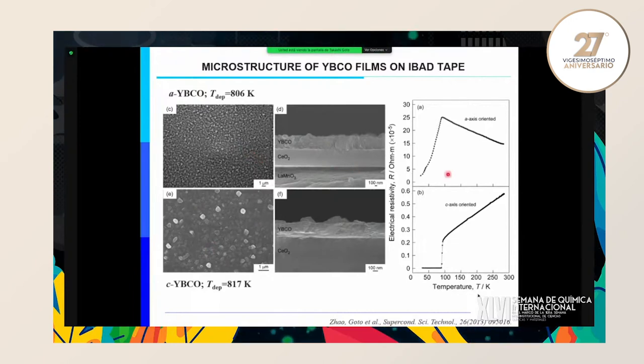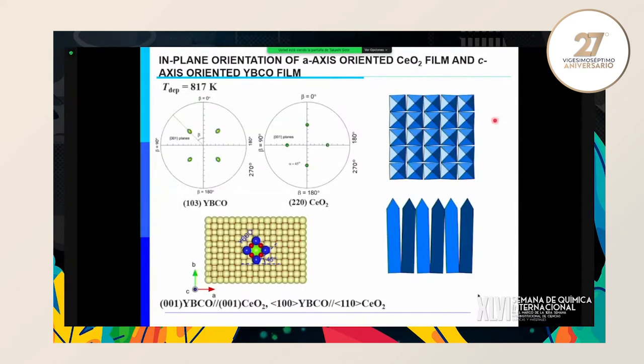But the superconducting critical temperature of A-axis oriented YBCO is low, while C-axis oriented YBCO is high enough, about 90 K. So we have to make C-axis oriented YBCO film. The ceria and YBCO film have the same single crystalline orientation: the YBCO 001 plane is parallel to the ceria 001 plane. It looks almost single crystalline by pole figure, but is still distorted. So we have to make the YBCO film as little distorted as possible.